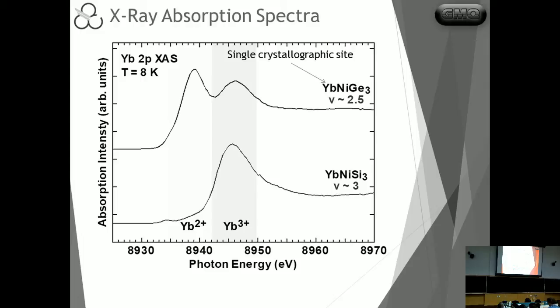When you do this type of absorption, indeed you can see in the germanide that there's a clear signature of both types of ytterbiums. If you work out the average, it should be around 2.5, while the silicide seems to be basically 3+. We don't really see much of a signature here of the 2+. But since there was an indication that there should be some kind of hybridization here, these collaborators went into more detailed experiments to try to solve that.